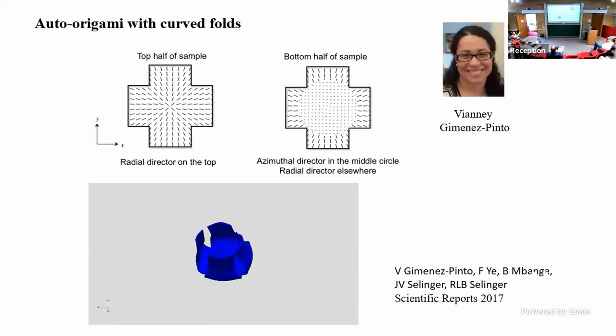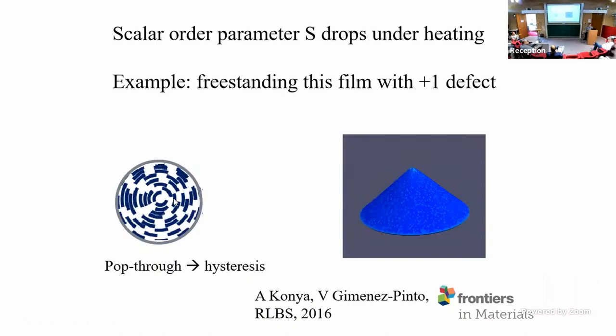The mesh seems to be a uniform mesh. You have to adapt the mesh size to deal with the singularity. No, but the curvature right at the top might depend on our mesh size. Oh, the other issue is there's a nematic director, right? And to the extent that the director is associated with each tetrahedral element, that means there's a core size for the defect, which is related to the mesh spacing. So in principle, we could refine the spacing right at the tip and get it sharper. And you could make it adapt as it goes along.